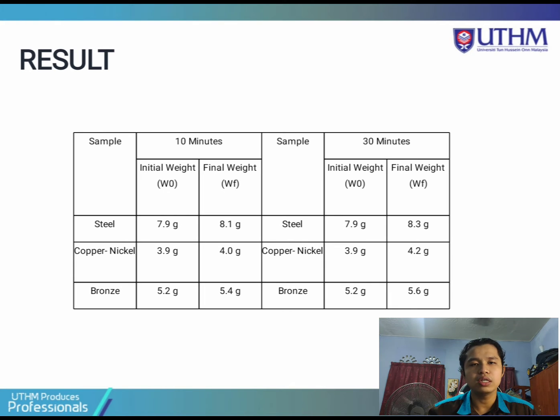So after running the experiment, we obtained the values of weight before and after. We can look at the slide, where the initial weight of the steel is 7.9 gram. After running the experiment for 10 minutes, the final result increased to 8.1 gram for the steel. After that, we used a copper nickel sample, where the initial weight is 3.9 gram. For the final weight of the copper nickel sample, we obtained a weight of 4.0 gram, which is an increase of 0.1 gram. For the bronze, the initial weight is 5.2 gram and the final weight is 5.4 gram.